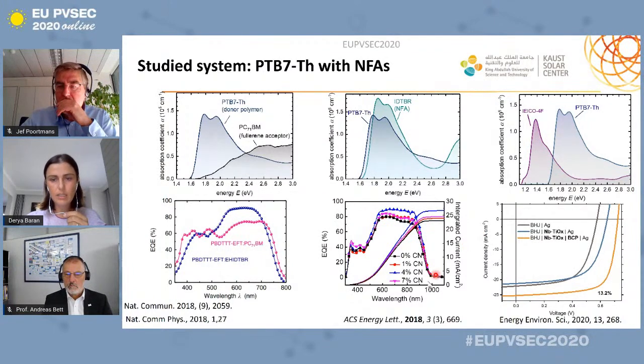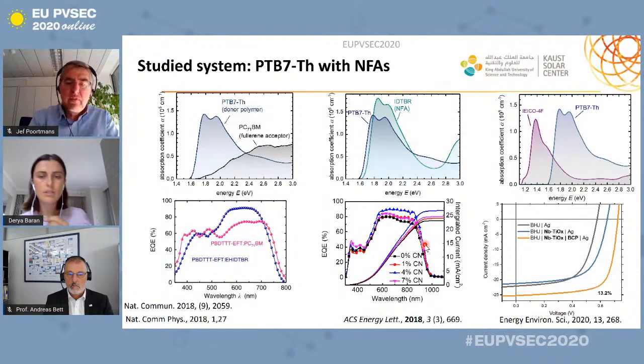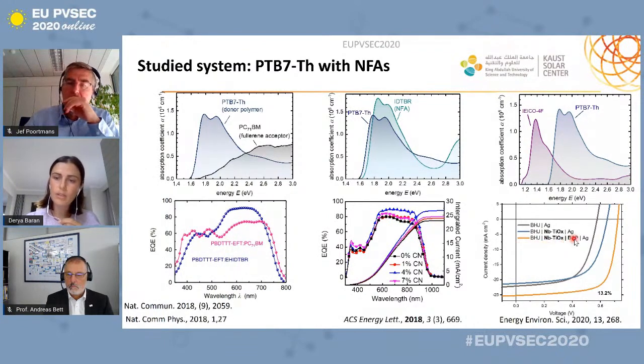And obviously, as you see here in the EQE, the band edge now is much lower, and we improved the power conversion efficiency simply because of utilizing the low energy of the spectrum, and got 12.8% solar cells. And by combining it with a novel solution-processable bilayer transport layer, we further increased this ohmic contact in these devices and improved the efficiency up to 13.2%. And this unique bilayer ohmic contact has been used in several different technologies, not only in OPV. It was working quite well with perovskites, transistors, and we recently published it in Energy and Environmental Science as well.